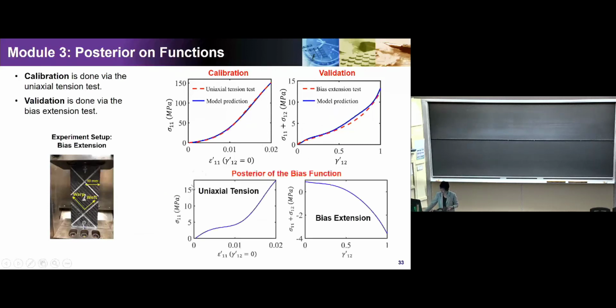Then we computed the posterior on the whole function, which means we start to quantify the uncertainty of the bias function. You can see that the bias increases as the strain epsilon goes up, and the stress level increases. This also shows that when the shear angle increases, the bias goes lower. The interesting part is the validation, where we now use the bias extension test data, when gamma is not equal to 0 anymore. You can see there is still some variation in the prediction after the model updating, but in general that kind of uncertainty is quite acceptable. So this is an example which tells us that it's interesting to use uniaxial tests in two directions.